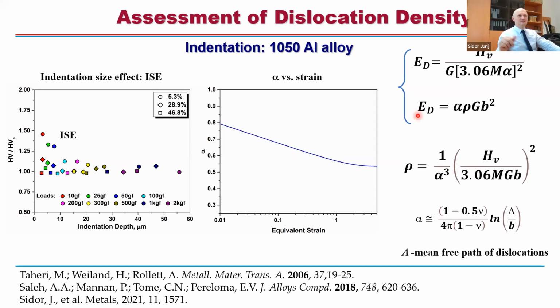Okay, and from the other side, you know that the stored energy is nothing else but alpha times rho, the dislocation density, times G b squared. When you combine these two equations, you get a new equation, this one, right? So all parameters you have: HV, this is the hardness. Alpha, you calculate. You use either the Taylor factor, which you measure based on the texture. G, and b is the Burgers vector, which is also known.